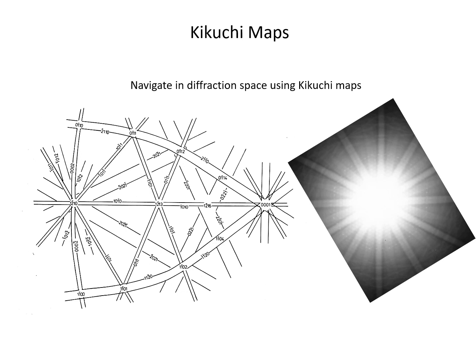So it's kind of weird because it's not a spatial variation now. In this particular instance, it's an angular variation. When we're in this mode, we're actually in the Fourier transform of real space, so we have to think in terms of angles. And that's what one does. One navigates around in reciprocal space.